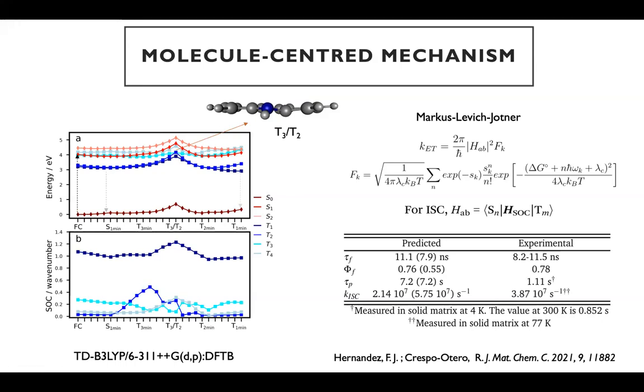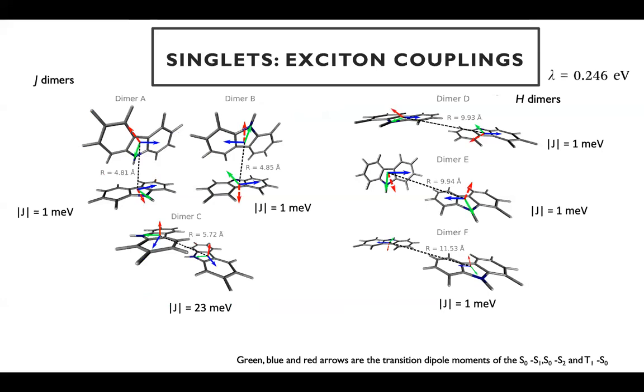Essentially, we can say that the mechanism that we are proposing is this: we have initial excitation to the excited state, relaxation, decay through a triplet state, and then we can have emission from either the T1 or T2 state. So what happens when we move to the solid?